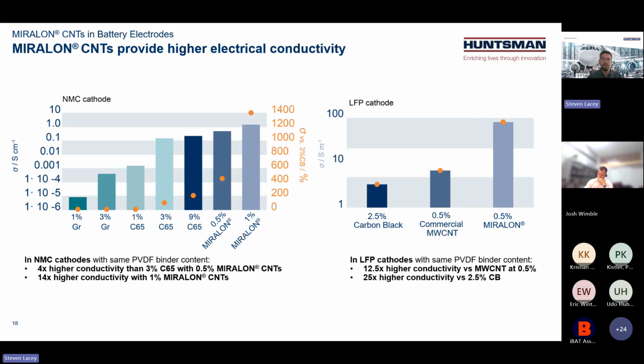Now, when we go to the electrode level, we can already see improvements. So we measured electrical conductivity of both NMC cathodes and LFP cathodes with different conductive additives. So carbon black as well as graphite as a reference on the right, as well as carbon black and multi-walled CNTs on the left. So for NMC cathodes, we can see that at the same binder content, we have 4 times higher conductivity than carbon black using 1/6 of the amount of material. And when you increase to about 1/3 of the material, we can get even higher electrode conductivity, 14 times higher.